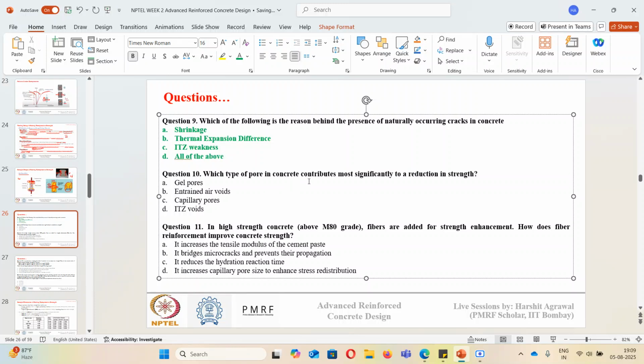Which type of pores in concrete contributes most significantly to the reduction in strength? It is the capillary pores. Capillary pores are basically the macro pores present in concrete. Pore distribution in concrete is of different sizes, in which macro pores generally correspond to the capillary pores. Capillary pores are formed due to the excess of water that we add during mixing. And if there are more pores inside the concrete, lower will be the strength or the load bearing capacity of concrete.